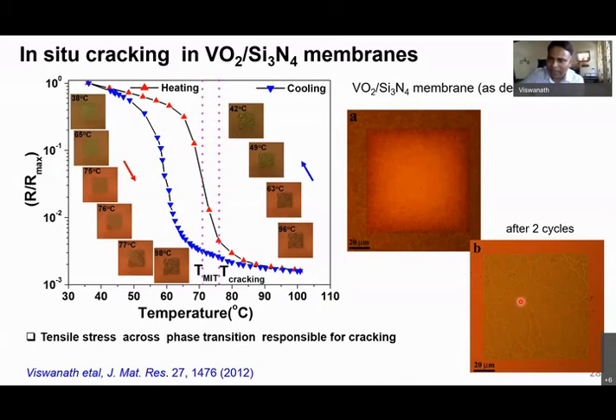In the same paper, we also found a lot of twinning, but we are not very sure whether it is twinning associated with the phase transformation for strain accommodation, or crack-induced twinning. Typically crack propagation, I tried with a high-speed camera, happens at a velocity like sound. There are papers suggesting that due to crack propagation you may achieve the critical stress required to induce twinning. Again, the paper was not conclusive. We are just left with the observation of cracking and the evidence of twinning, but it was not conclusive.